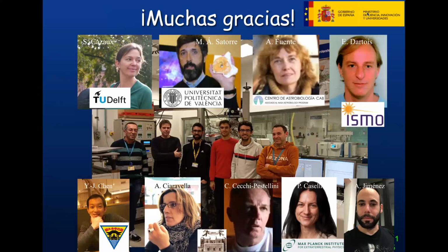So I am interested in whether there are laboratory experiments on an intimate mixture of amorphous dust, like the cometary dust, and water ice, that can be used to compare to what is observed, because as soon as the object is almost fully covered by dust, my hypothesis is that there is still some water ice mixed with this. You have a very shallow 3 micron band, similar to what we observe in Churyumov-Gerasimenko, for example. But some authors claim that this is not water ice; it is something else. And I'm not sure if there are experiments in the lab.